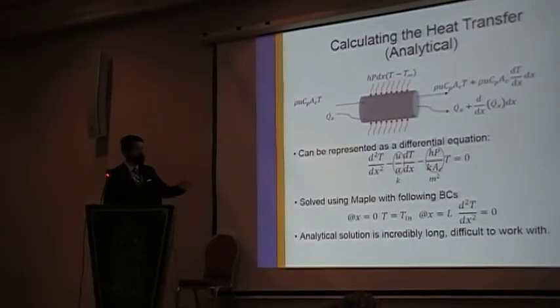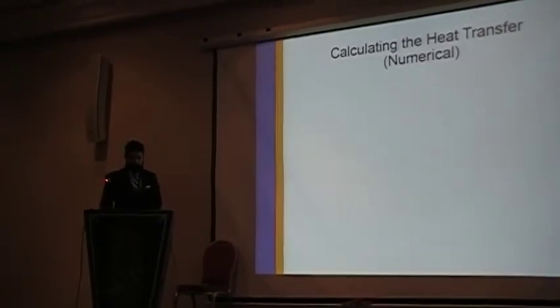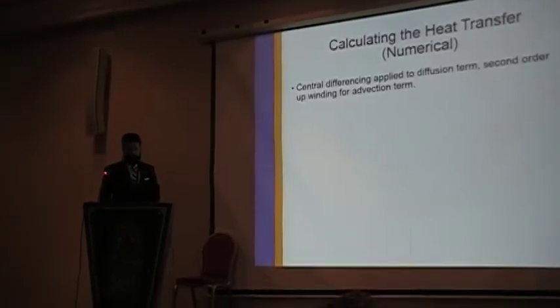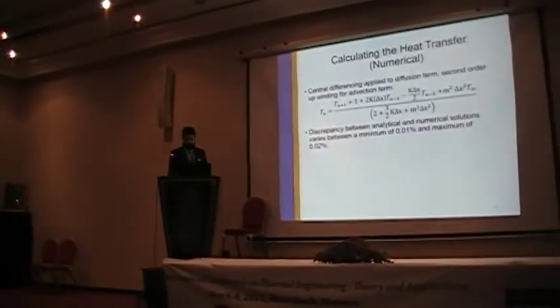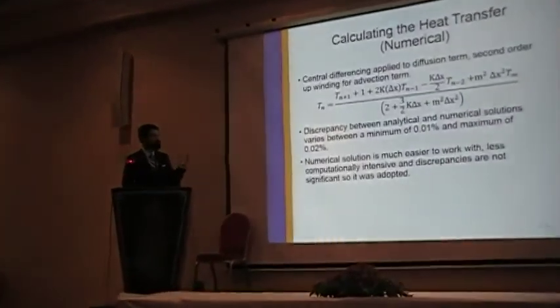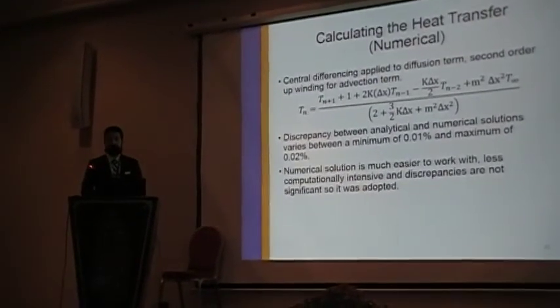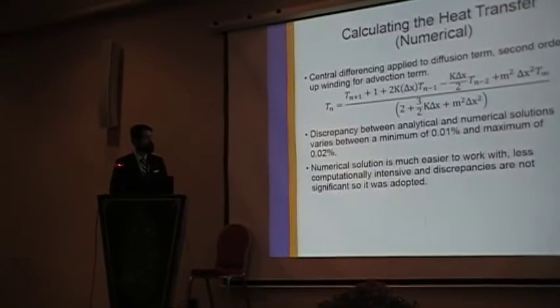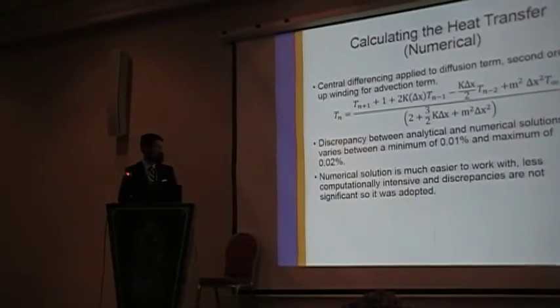After solving this, we end up with a very long and difficult to work with analytical solution. It would take up an entire slide, and it's tons of exponents, so it requires quite a bit of computational power. For this purpose, we developed a numerical solution as well. It involved taking the same differential equation and applying central differencing to the diffusion term and second order upwinding to the convection term. This gives the following discretization. When we compared the analytical and numerical solution, we found that the discrepancy between them was almost non-existent. So for this purpose, we chose to continue with the numerical solution because it is far easier to work with. It's very light computationally. The computer can chug through it in a couple of seconds.